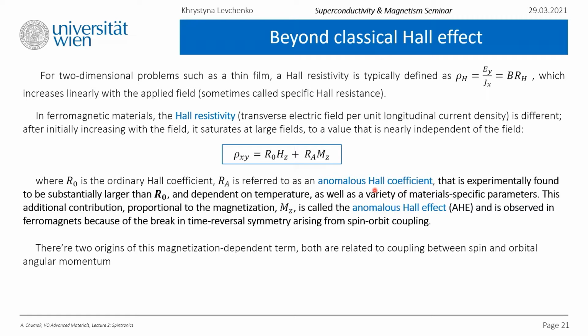There are two origins of this magnetization-dependent term, and both are related to coupling between spin and orbital angular momentum. Extrinsic, disorder-related, due to spin-dependent scattering on impurities, and intrinsic. And in such an experiment, charge carriers acquire an additional contribution to their group velocity perpendicular to the electric field and hence contribute to the Hall effect. We will see it further on the example of gallium manganese arsenide.